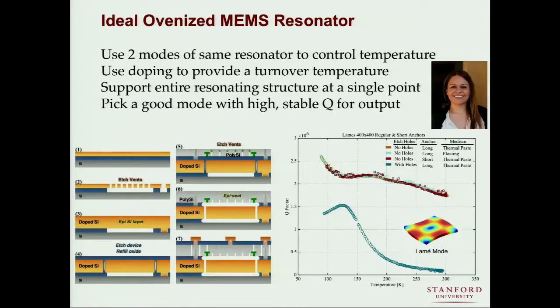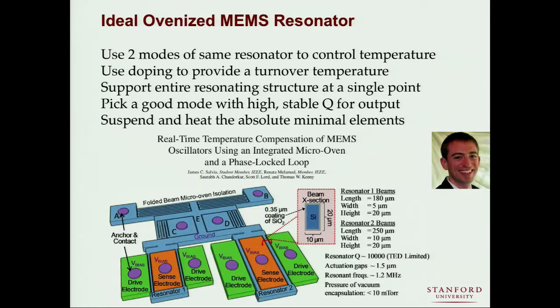You want to pick a good mode. You'd like a high Q, high frequency mode that doesn't have a lot of temperature dependence to its dynamic properties. So we can fix the temperature coefficient of frequency with doping. Temperature coefficient of quality factor is another issue here. And if you're limited by thermoelastic dissipation, you've got a pretty strong TCQ, which is annoying. We found that if you build parts that are bulk mode resonators with no vent holes, you get into the limit that seems to be Akhiezer damping limited. And it looks like the temperature dependence of the Akhiezer damping is much smaller. So you have a system that's more easily operated over a wide temperature range.